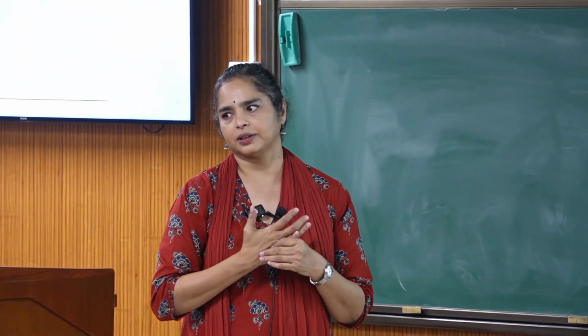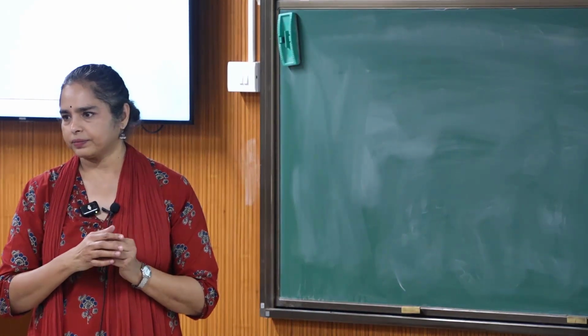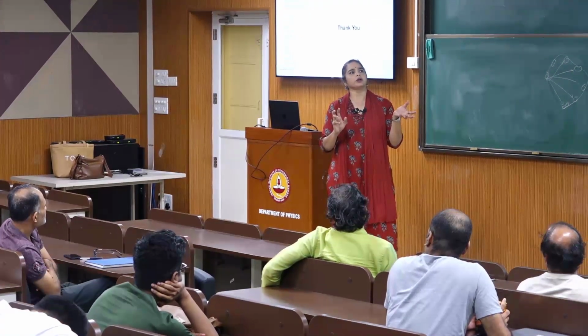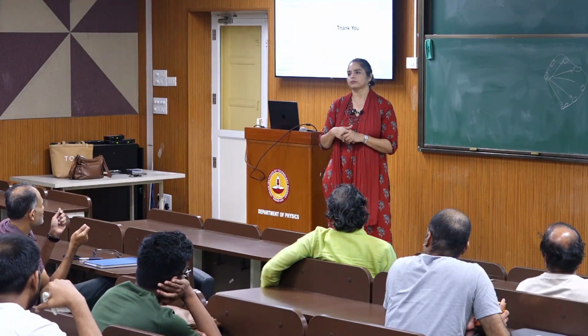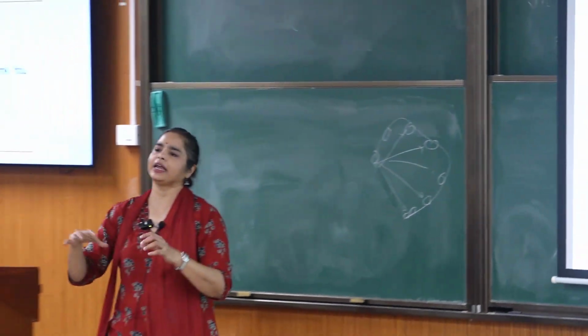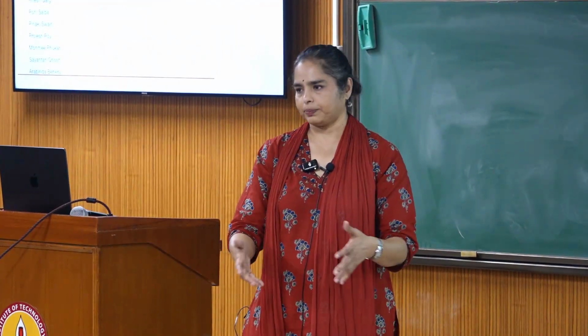So, yeah. The scaling laws that you suggested at the beginning, do they change in the presence of Crowders? No, they don't seem to. For example, a polymer collapse because of self-interaction and a collapsed state of a polymer because Crowders are there, it's still n to the power of 1/3. The Crowder is basically effectively increasing the attraction. So again, in any mechanism in which there is an effective increase in attraction, however it comes, a collapse seems to happen. In my free energy term, I just have another free energy with the Crowder. That's all. So the scaling laws don't seem to be affected. It's still n to the power of 1/3.